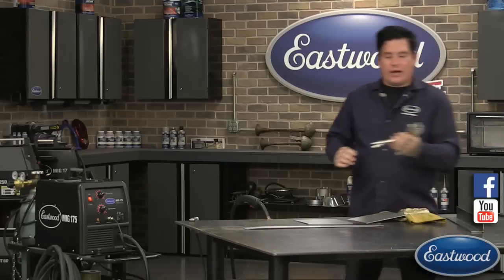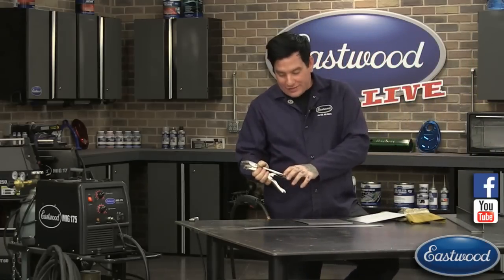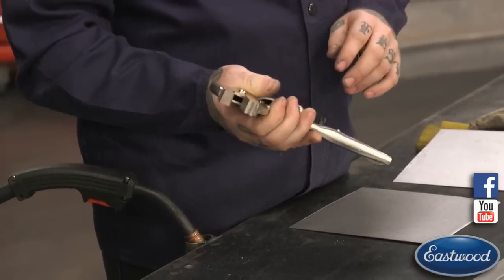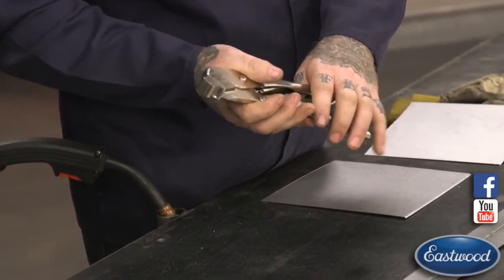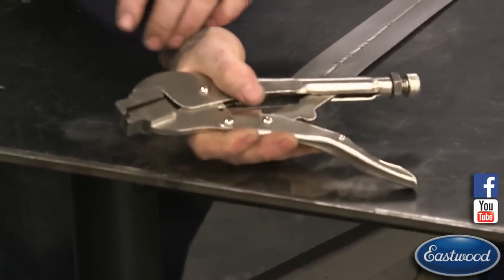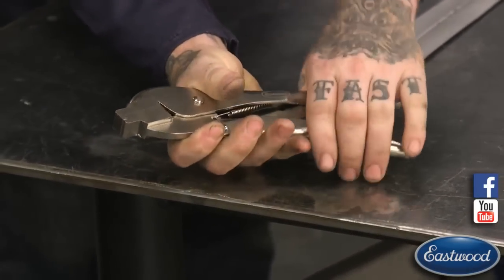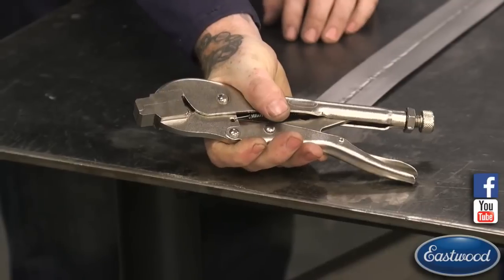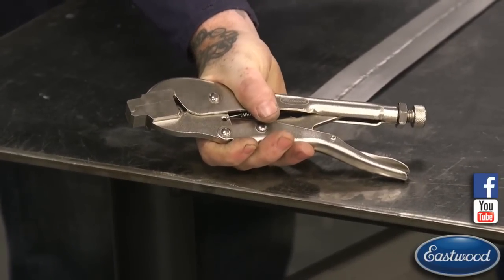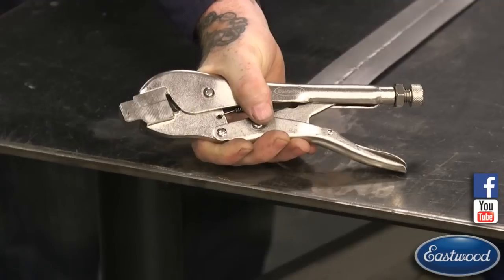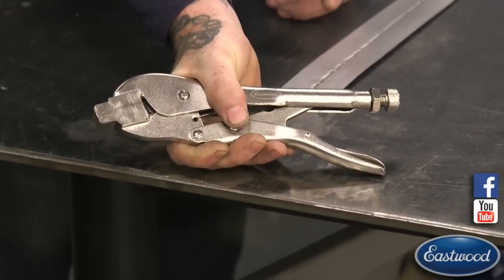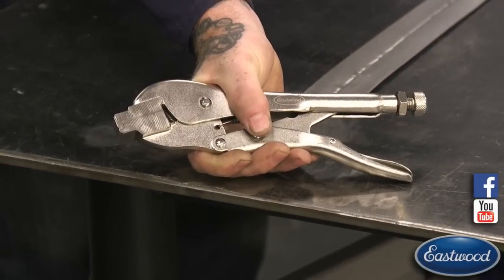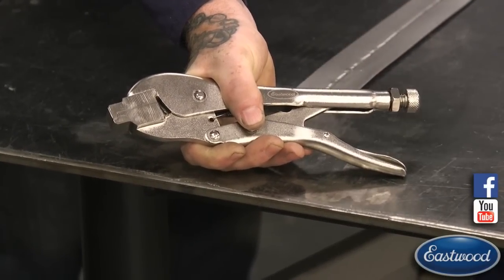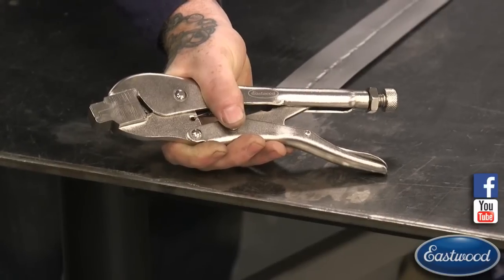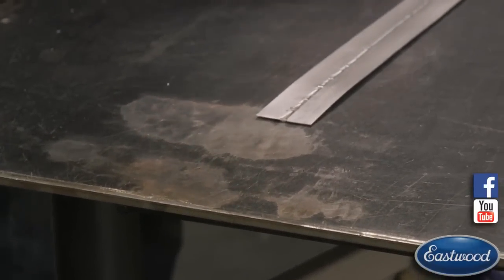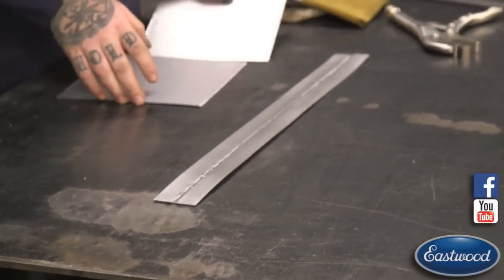You have these cool little pliers here called the Perfect Panel Prep Tool. Whew, I knew I was going to mess that up. So the Perfect Panel Prep Tool has these cool little jaws here that are shaped in such a manner that it puts a little bevel on your panel. So what you can do is you can put the same bevel on the panel every single time. And with these pliers, you can quickly go over a patch panel on both pieces, and you can put a little bevel in each piece, which gives you a little valley to leave your welds in, and requires almost no grinding at all if you get your machine set up right.